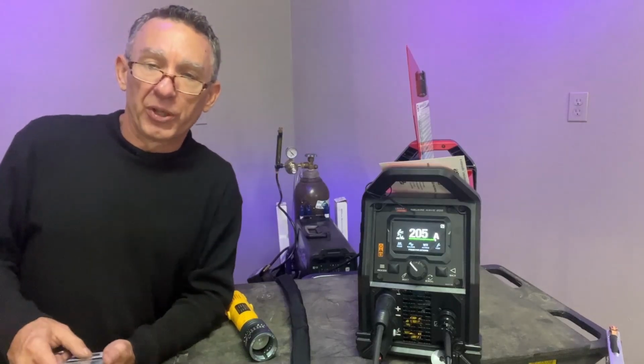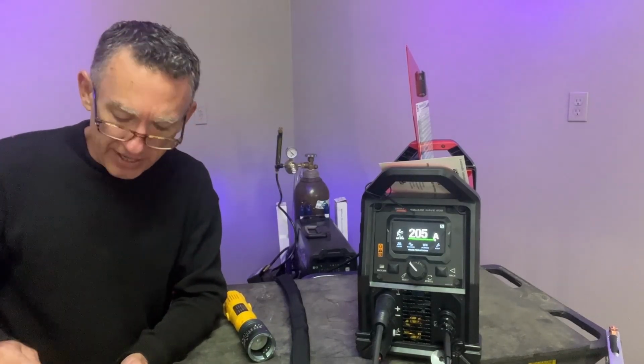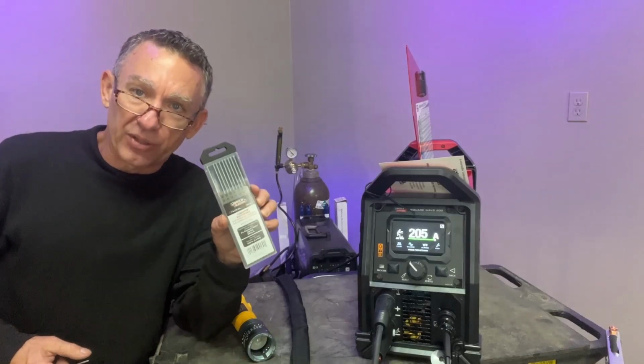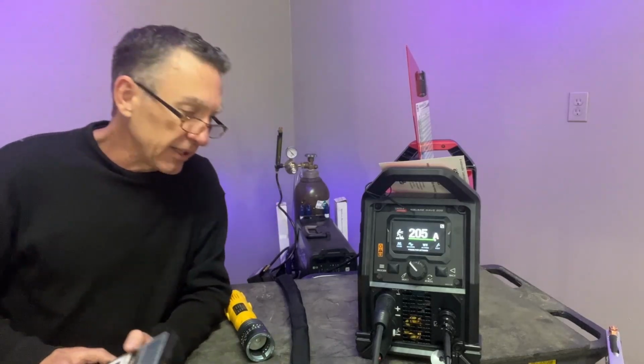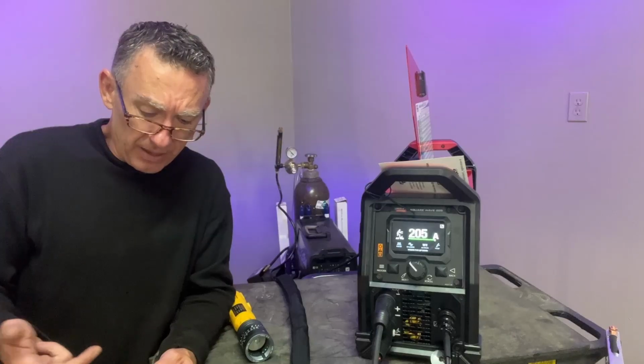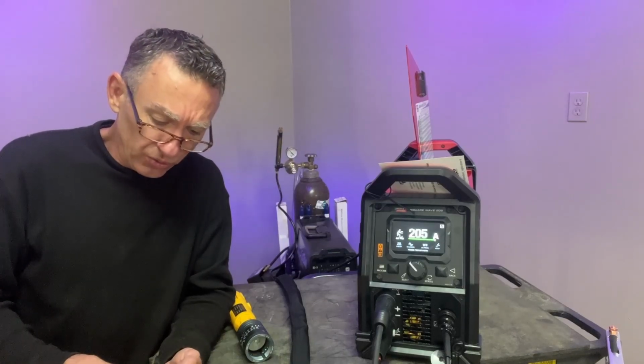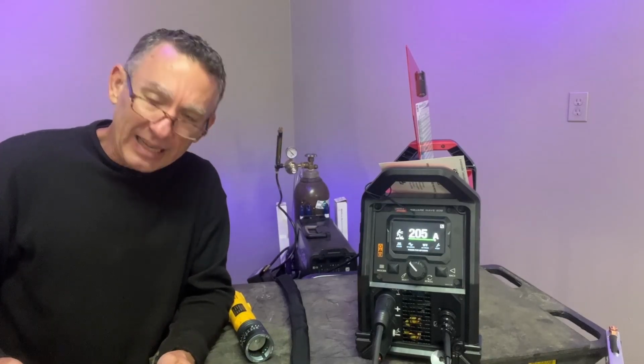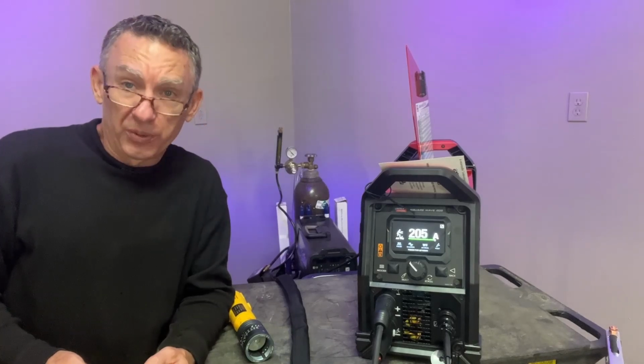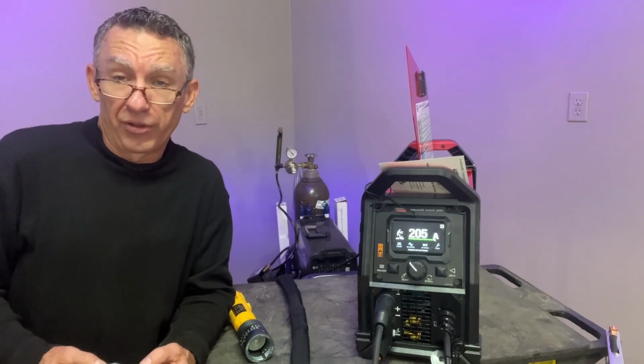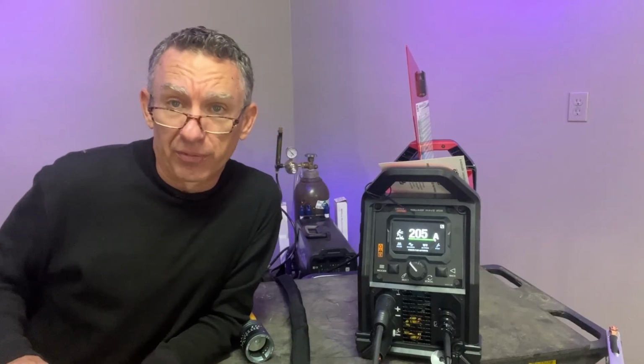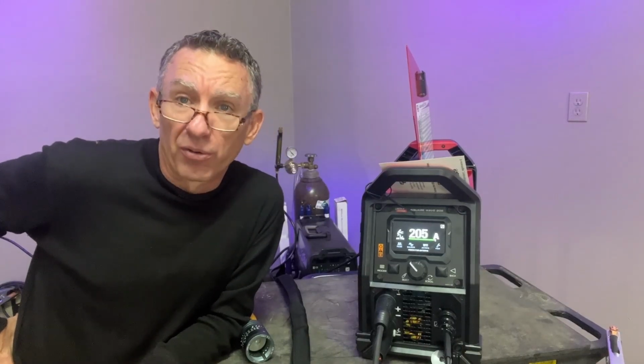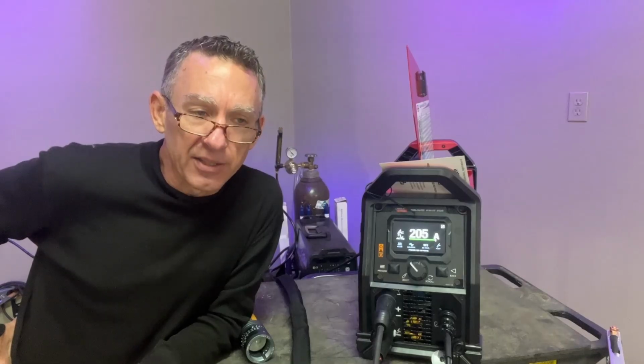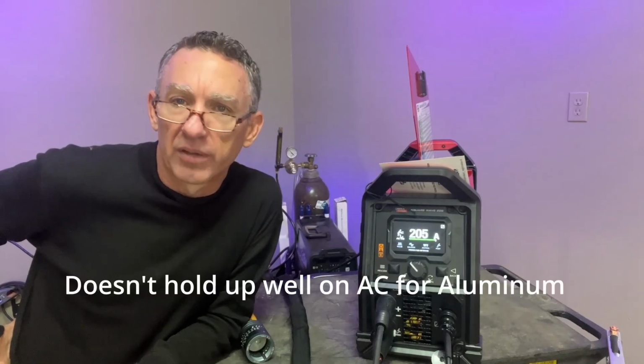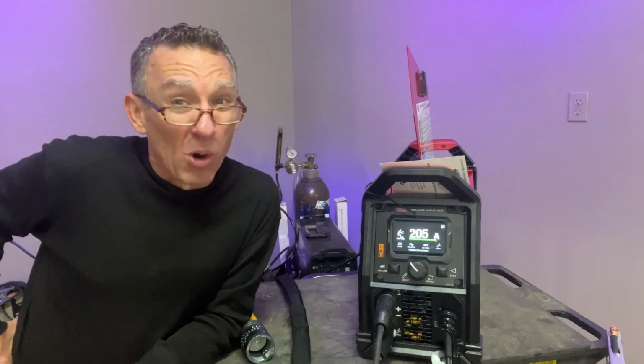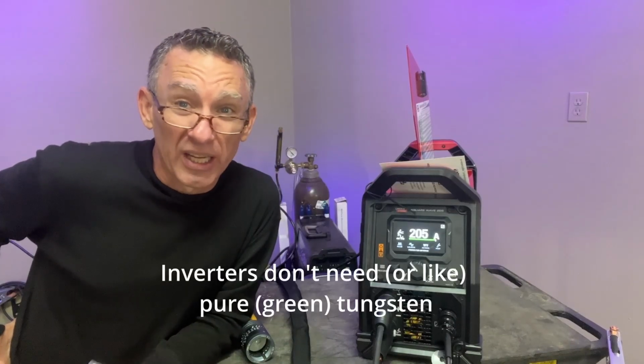So while the machine comes with 2% lanthanated electrodes, which are all fine and dandy, I happen to have a box here of 3/32 2% ceriated tungsten electrodes, and I really think there's a number of tungstens that you can use. I standardized on cerium back in the late 90s, and I really hadn't welded with anything except red or green, right? The old rule of thumb was you use green tungsten for aluminum, and you use red tungsten for everything else. What we found in the late 90s with inverter technology is red tungsten doesn't hold up very well. And green tungsten wants to form a ball no matter what, right? It's a consequence of using it.